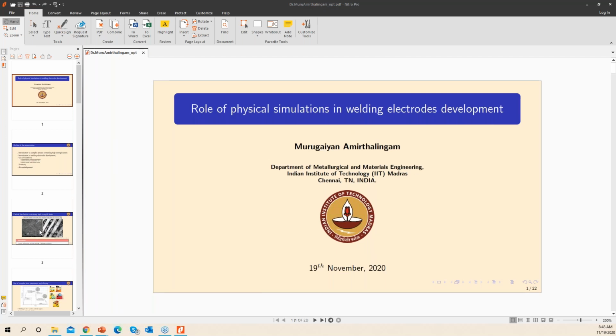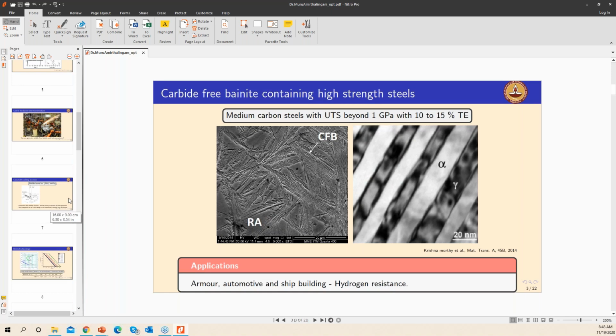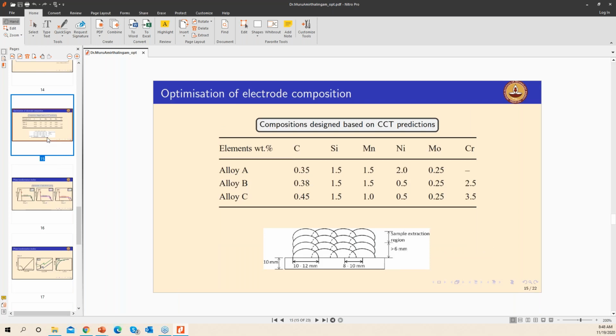Okay, so yeah, thanks, Dan, for pulling this slide. Maybe you can move on to slide number, maybe 15. Okay, here we go. Yeah, so you see over here, there's a multi-pass deposition of what we made. When we are defining interpass temperatures, we have to ensure that the first weld pass is not cooled to room temperature. If you directly cool to room temperature without isothermal bainitic holding, then it may transform to martensite, an all-martensite microstructure. So then it may crack. So we should not let any part of the weld cool to room temperature. So the identification of the holding temperature is very critical. We hold it at isothermal bainitic holding, and then we deposit the next pass. After depositing the next pass, again, the weld is not cooled to room temperature. We maintain it at that temperature.